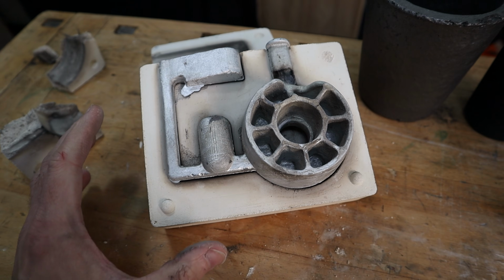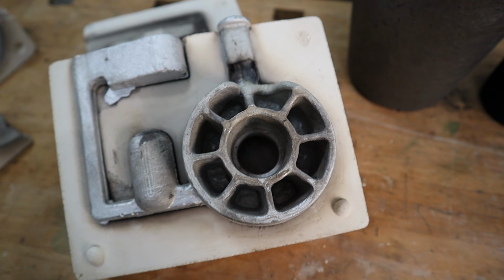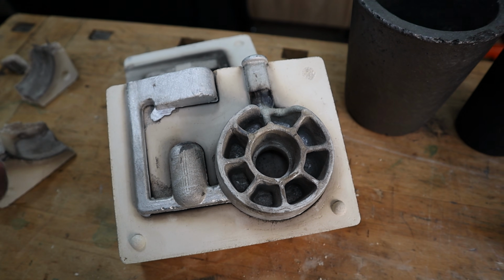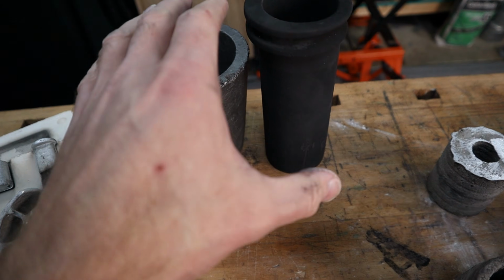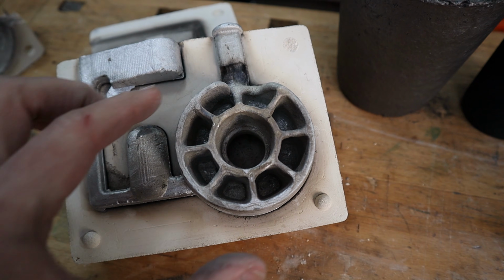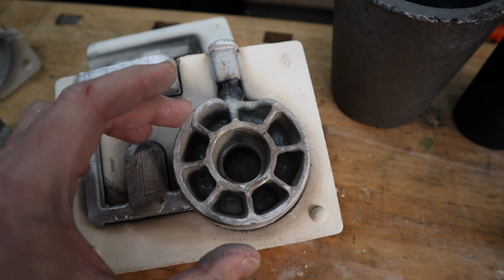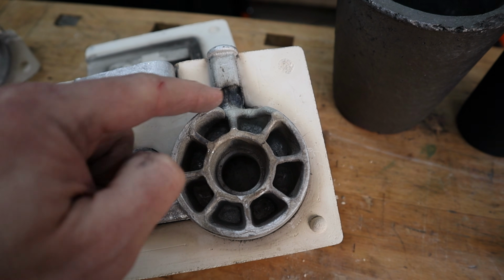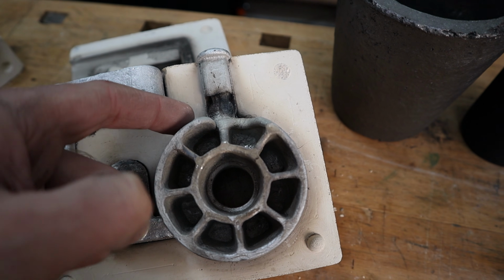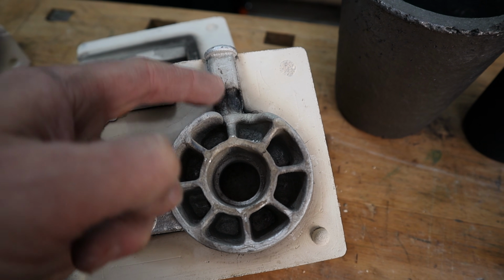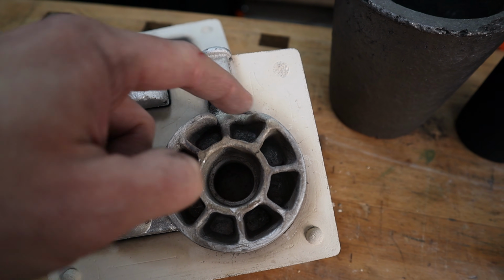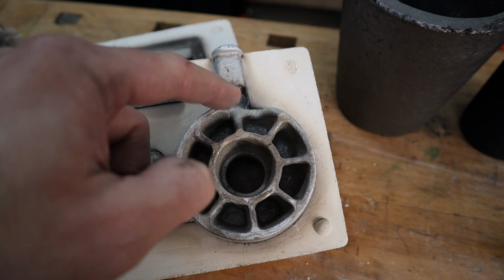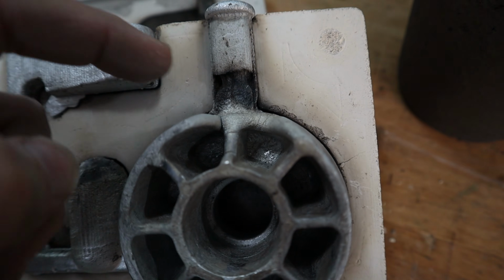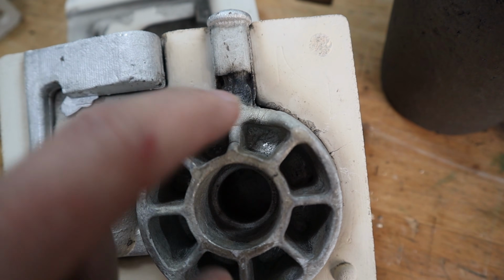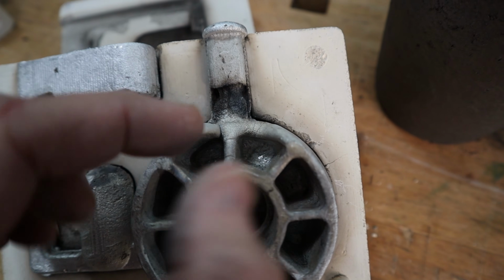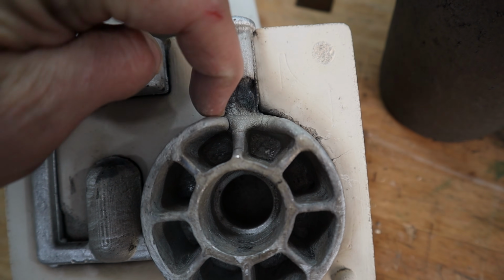Now if we take a look at the plaster version, it's not perfect because we didn't get the connection at the top, but the issues are the exact same. We did not have enough material. I was trying to save material in here, and because of that we had two problems. One was we had this area cooling too quickly. So it found its way up the riser, up the vent, much more easily than completing this section, because it had cooled too much by that point. We also had a little bit of a cold shut in here too, so we had an oxide layer forming here and here. As it tried to merge, it could not merge completely.